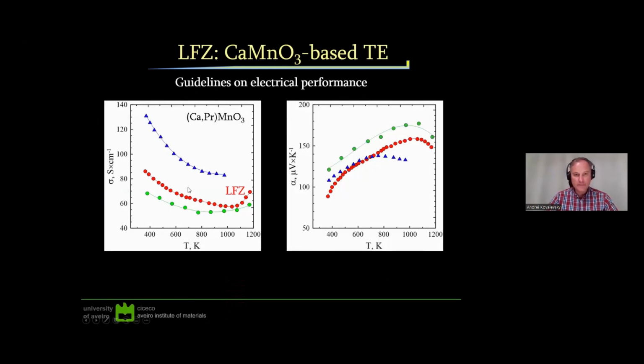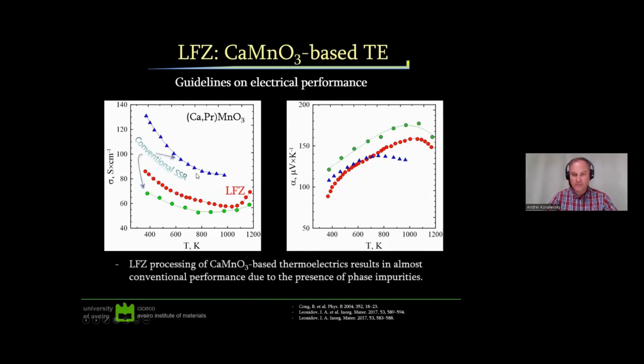So what about the electrical performance? Again, the red curve corresponds to our material grown by laser, and some literature data, and you can see that the results are not so interesting as in the case of the 349 phase. So here we are somewhere in between conventional processing methods. This happens because we cannot avoid, we cannot dissolve those inhomogeneities which exist in our material during processing. Here we need some kind of additional optimization of this process.